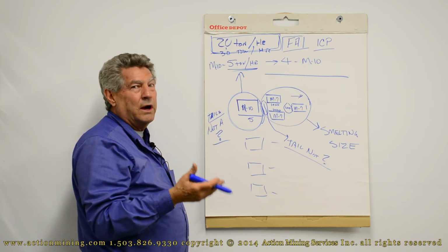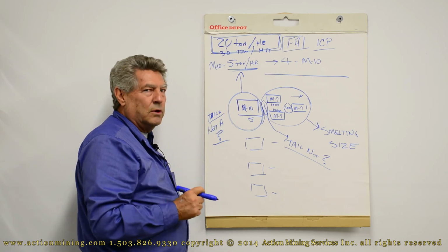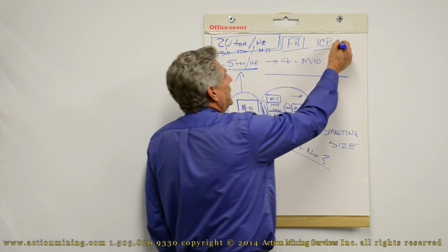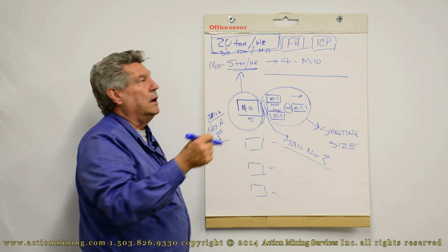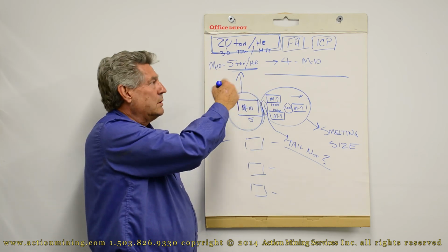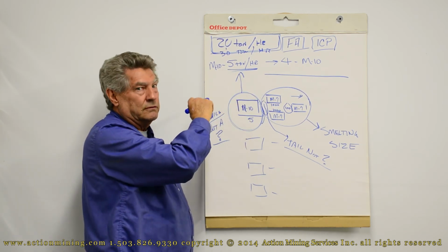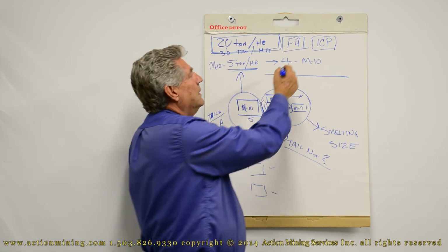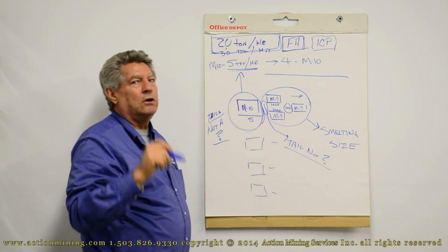It's reading really well on their ICP. They have calibrated and everything's running well. Well, it's showing a bunch of gold chlorides or something equally interesting. Well, this ain't it. This ain't gonna work. Now you're into leaching or something equally interesting, which is very expensive under the best conditions. A fire assay, if you can fire assay it, it is recoverable gold.